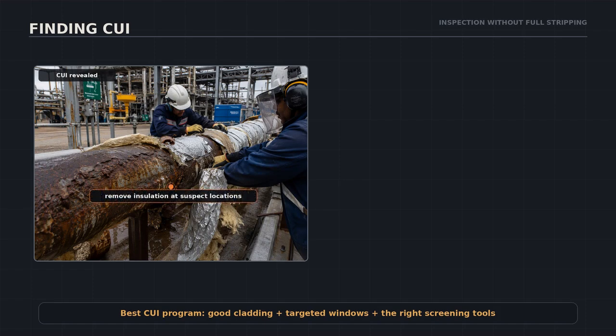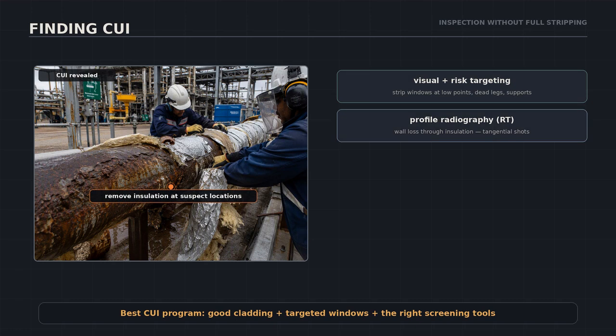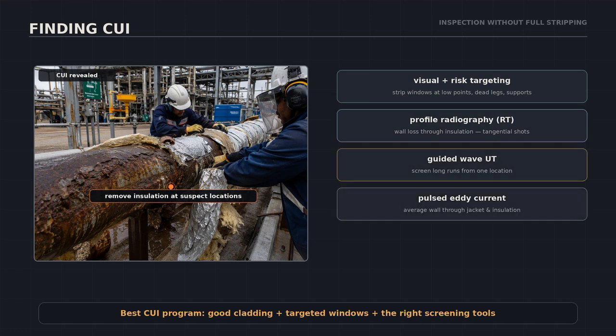So how do you find CUI without stripping every meter of insulation? You target. Risk rank the lines: age, temperature, cladding condition. Strip windows at the likely spots: low points, dead legs, supports, penetrations. And screen the rest with tools that see through the jacket: profile radiography, guided wave ultrasonics, pulsed eddy current, and neutron backscatter, which finds wet insulation before corrosion even starts. Good cladding maintenance is half the program.